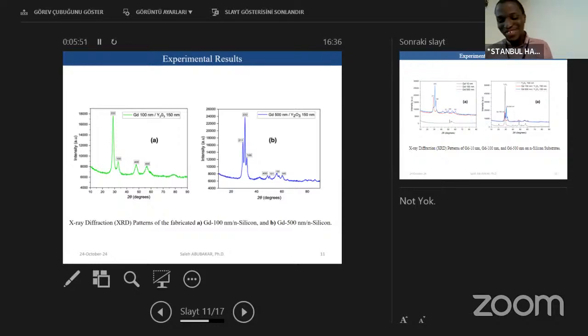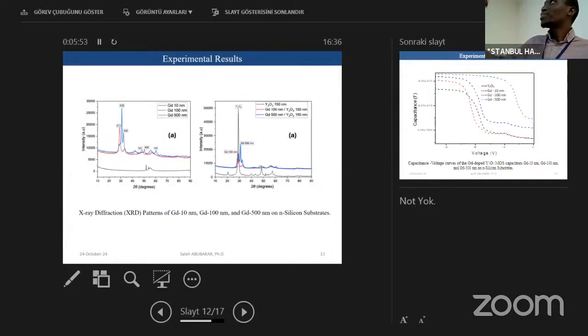I'm saying degree. I'm sorry for that. So we compare, as I expected, when you have the oxide material and you deposit a metallic material, either you get a shift in the angles or you reduce the intensity of the material. That's what we are looking for, and we get it.